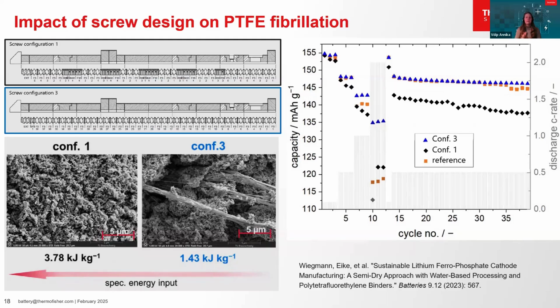However, now let's examine the cycling capacity of half cells made from these materials compared to a wet cathode mixed in a planetary mixer as a reference, shown in the graph on the right. The cathode mix without kneading blocks in blue exhibits the highest capacity at all cycling rates over 40 cycles. The cathode mix with 5 kneading blocks in black has the lowest capacity and cycling stability.